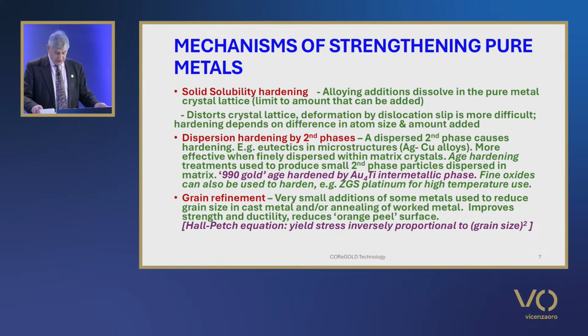It is also worth noting that dispersions of metal oxides, carbides, and other ceramic particles can also be used to strengthen metals. An example in precious metals for high temperature application are the oxide dispersion strengthened platinum alloys such as ZGS or ODS platinum, where zirconia or ceria or similar oxides are used. Microalloys, where very small alloying additions result in considerable hardening, also fall into this category of hardening by dispersed phases.